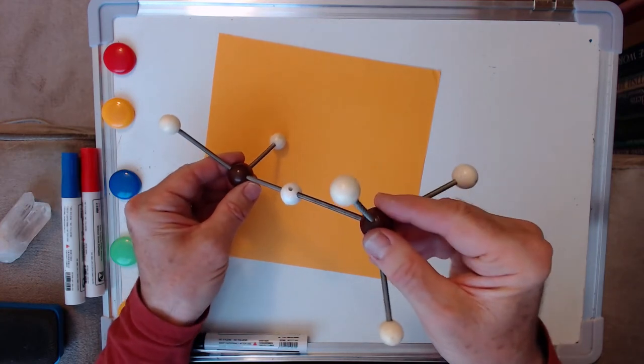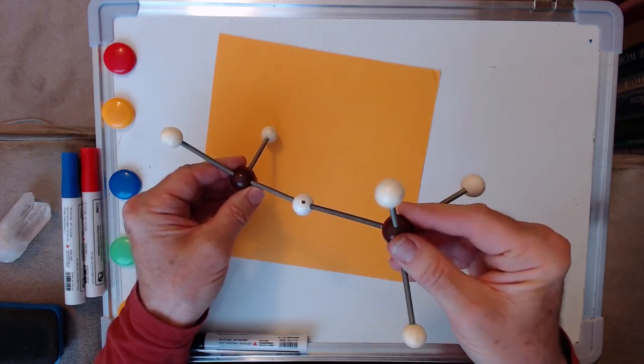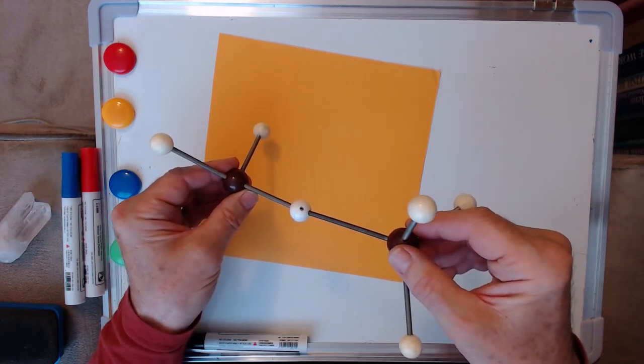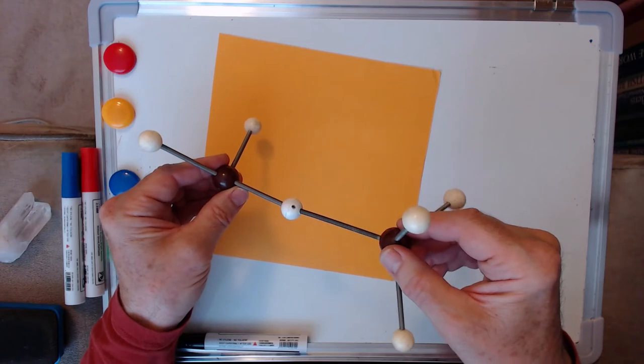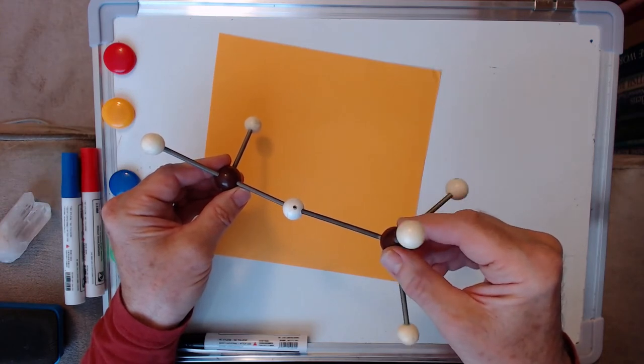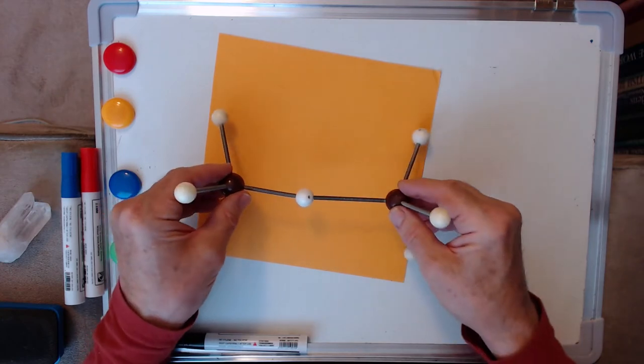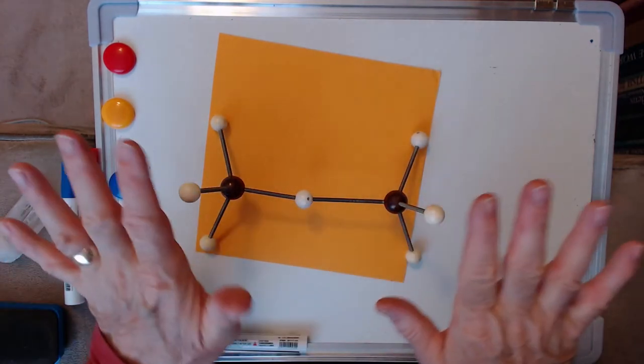So we get a slight angle between one of these units and the neighboring one, or we can allow these to rotate a little bit. And by a little bit I mean only five, maybe ten degrees, so quite a small amount. But as soon as you've done that, you've taken away the regular three-dimensional structure and you've created something that is now not a crystal but is amorphous.